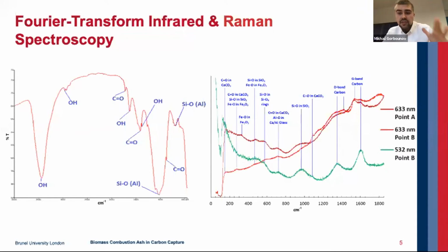Moving on to the Raman spectrum, the same limitations are evident. The covalent bonds are more prominently displayed than ionic bonds. However, there's still a myriad of information to be picked up from that. As can be inferred from the slide, the FA is mostly, once again, silicates, aluminosilicates, and carbonates. And the first two phases are confirmed by the peaks closer to the left part of the lower wave numbers. And the D and the G bands of carbon there indicate the sp2 carbon hybridization state present in the carbonates in the COO bond. However, previously unconfirmed bonds were also detected.